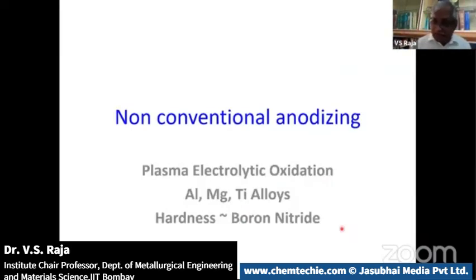Now we look at materials. Just now, I think probably Mr. Pandey was talking about titanium, aluminum, magnesium. These are very good materials, but they're very soft. How do I improve the hardness of these? In case you do this technique, the hardness of the surface can be as good as boron nitride. And boron nitride is one of the hardest things, very close to diamond, right? I can increase the hardness of this by using a non-conventional anodizing process. We call it the plasma electrolytic oxidation process.